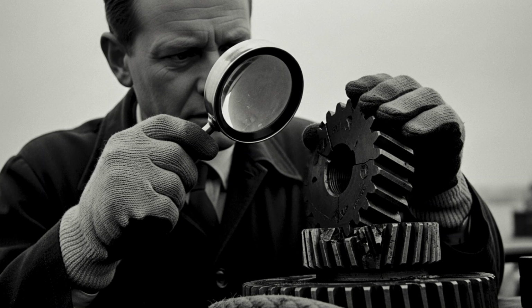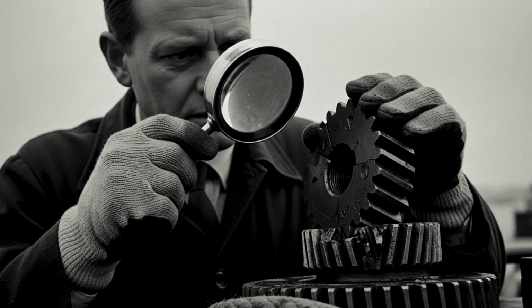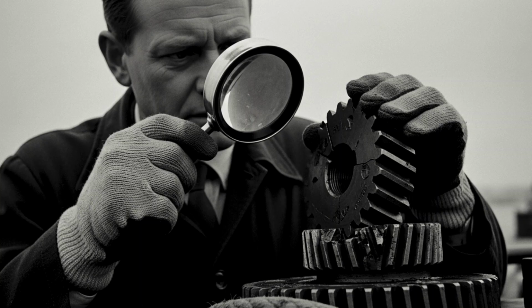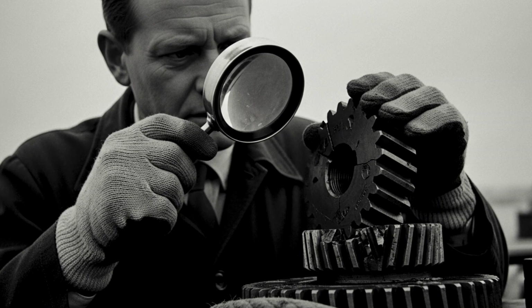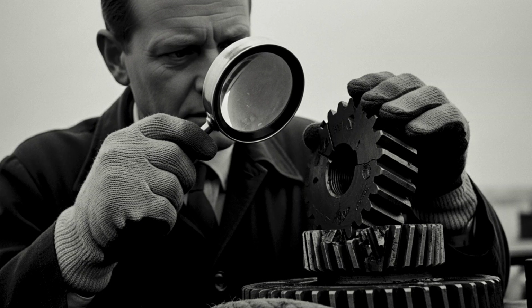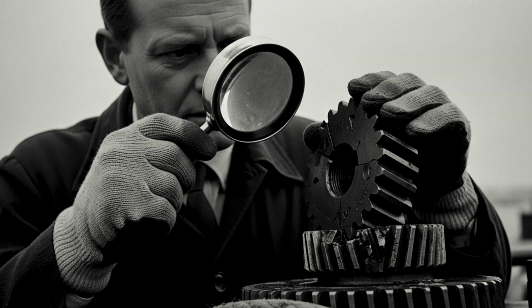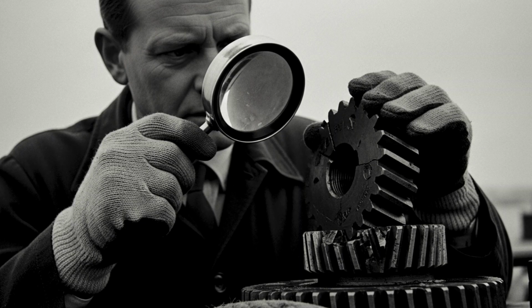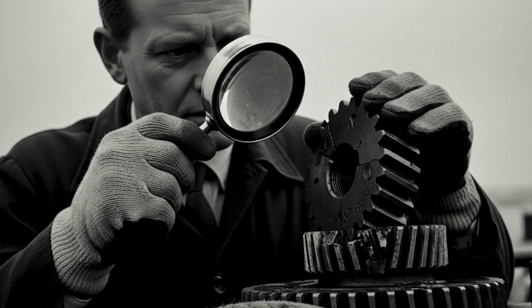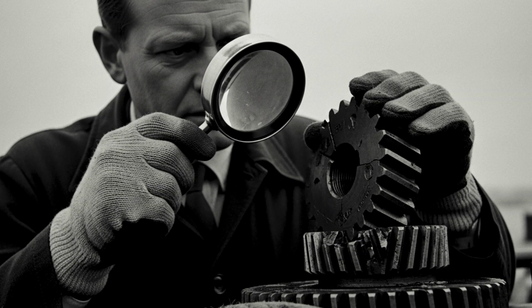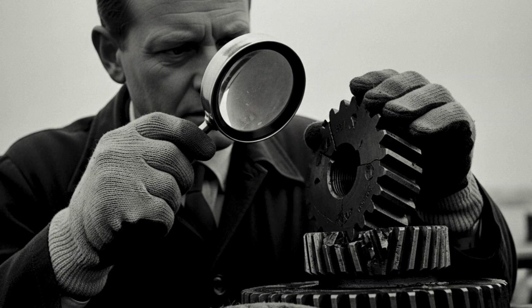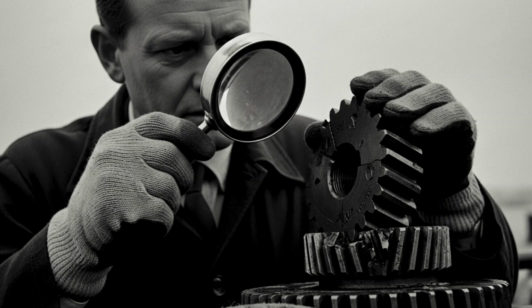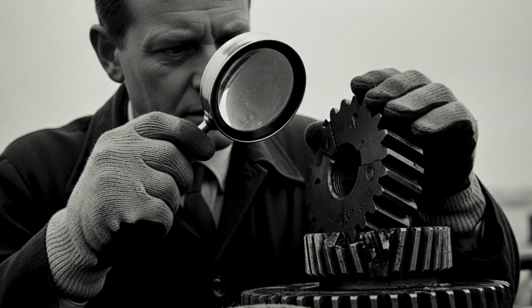A small amount of martensite is good, it gives strength, but too much makes the metal easy to break. This gear had almost only martensite and very little of the tempered kind, which means it had not been properly reheated afterward. It also had almost no retained austenite, another phase that helps make steel less brittle. This meant the steel was hardened too much and not softened enough. Tempering was supposed to fix that.